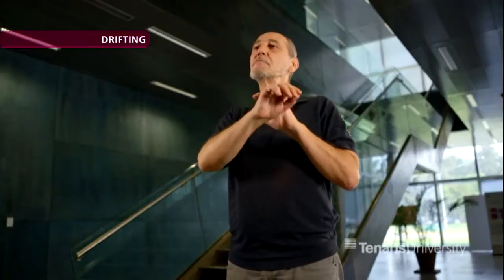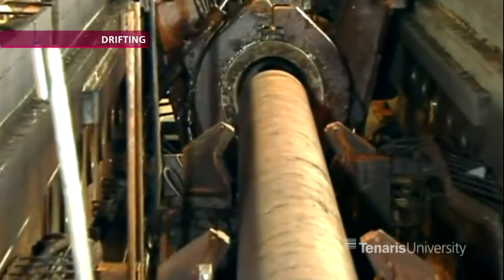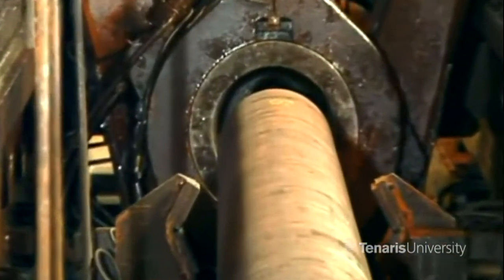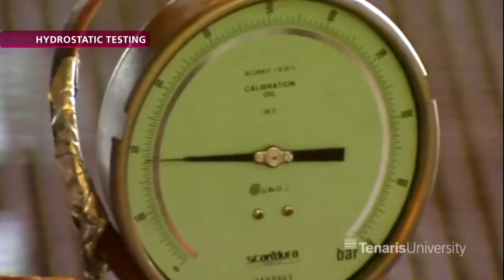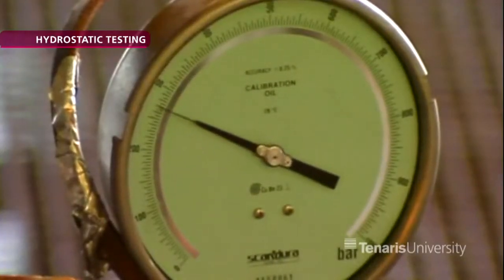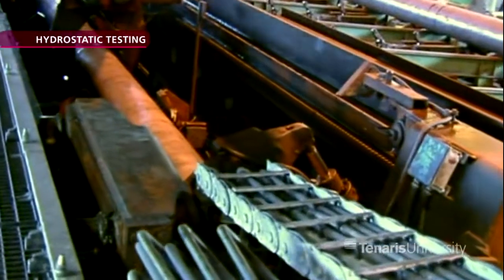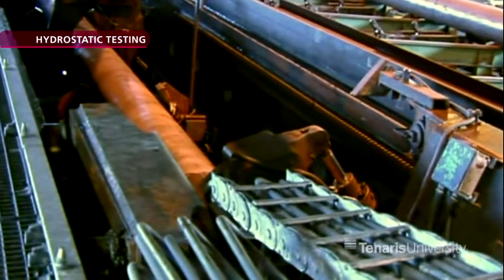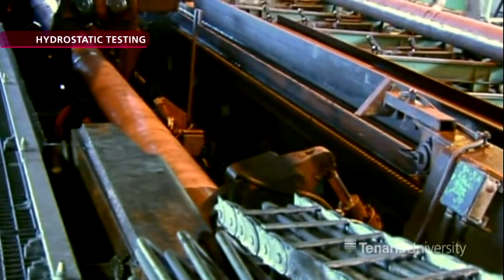Drifting is another finishing process performed to check the tube's internal diameter after the coupling assembly. A mandrel should pass throughout the full length of the tube without suffering any obstruction. To guarantee the mechanical integrity of the pipe, hydrostatic testing is performed. This process consists of filling the tube with a fluid, which is usually a water and oil emulsion.